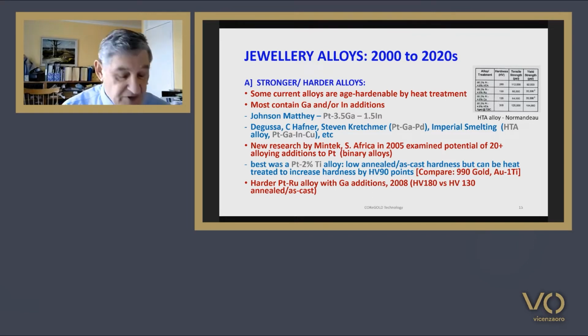Hard alloys tend to be difficult to work in manufacture, especially to set gems in mounts, and so it is advantageous if an alloy is relatively soft while being manufactured into a piece of jewellery that can be subsequently hardened to improve its durability while being worn by the customer. This can be achieved by age hardening heat treatment of suitable alloys after manufacture. This is a treatment involving precipitation of a dense dispersion of fine particles of a second phase within the matrix grains of the alloy.